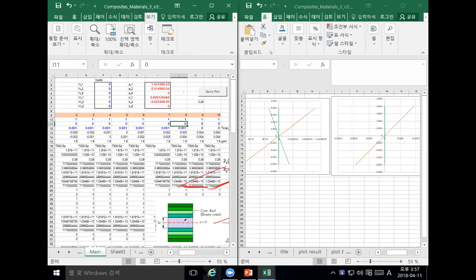All 0 degree, and a very important observation: strain-wise, with top and bottom, it's tension and compression. And the other one, this way, is the anticlastic curvature, compression and tension. Since this is all zero, all UD, there is no shear, no curvature, no twisting. Stress-wise, we only apply this bending, so there is no stress here, only this stress component. Deformation-wise, we do have this curvature, but stress-wise, only sigma one, since we apply this one. And that is the effect of the Poisson ratio, 0 degree.